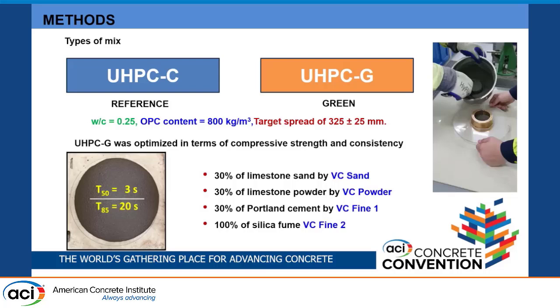So the concretes were produced with a water to cement ratio of 0.25, and we fix a cement content of 800 kilograms per cubic meter, and we establish a target spread of 325 plus minus 25 millimeters on the flow table that you see on the right, and it is the flow table used to determine the flowability of mortars, standard mortars.